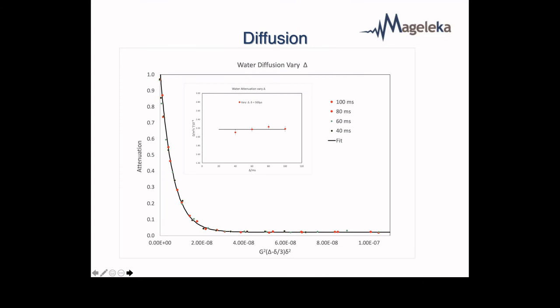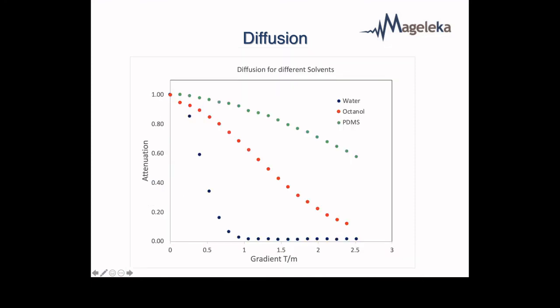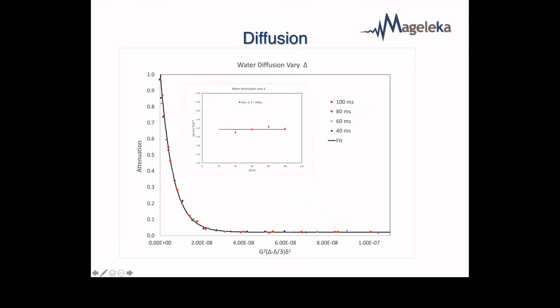Now, this time regime is something like 10 milliseconds to 10 seconds. It depends on the sample, but allows us to measure self-diffusion. And this is also a really powerful tool. So this is some experiments on water. And what we're doing in this experiment is measuring the signal height as a function of this parameter here. So the time constant of this curve is the diffusion coefficient. And what we're doing here is taking the diffusion curve from here and looking at how it varies with time.